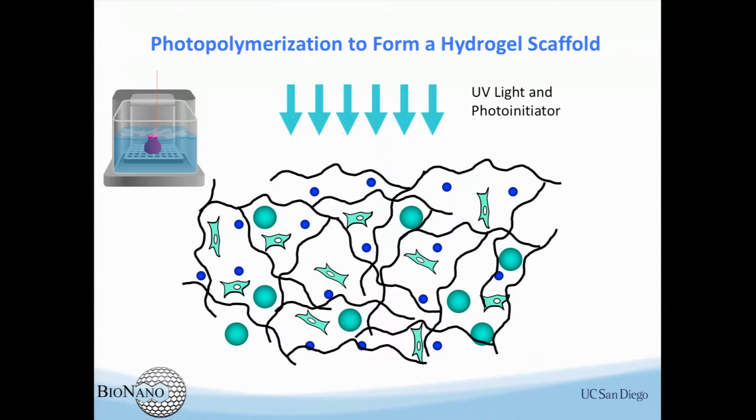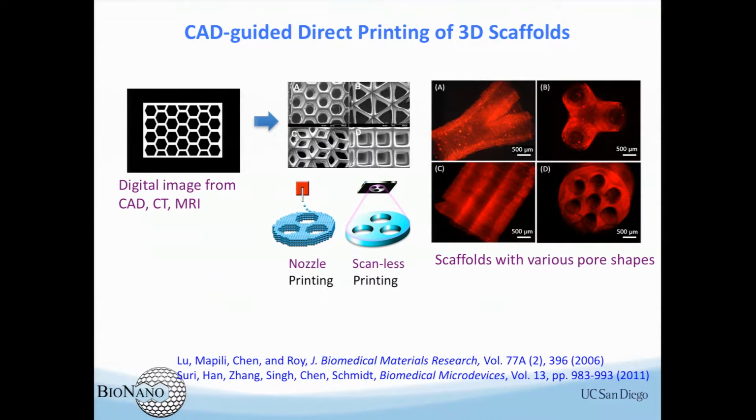It's very hard to tell where the cell goes, but you can tell where to polymerize the solution of these monomer chains. So it's very easy to do that. We actually started with PowerPoint software, when we didn't have good support from computer science at that time. If this is a PowerPoint slide with light, in this case a white color, you cross-link, you make the pattern. Without light, it's still dark, there's no cross-linking, it's still liquid, you can wash it out, right? And so just as simple as that, you can create different structures.